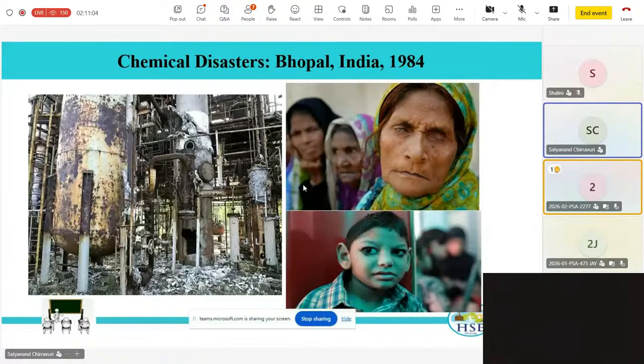And methyl isocyanate reacts with water. We know it's a highly exothermic reaction, but there's a controlled exothermic reaction wherein methyl isocyanate can react with sodium hydroxide. So there is supposed to be a vent scrubber. So methyl isocyanate, in case there is a vapor release, it has to be scrubbed off with the help of sodium hydroxide, but that also didn't happen. There was a failure there also. Methyl isocyanate escaped in the environment, and it resulted in the loss of nearly 20,000 people.